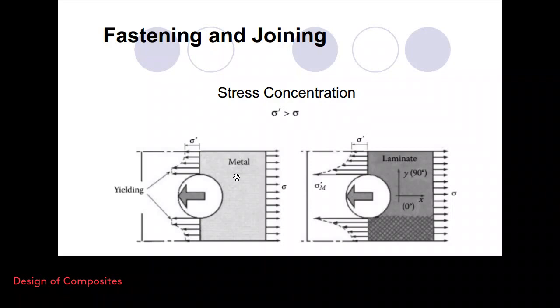Now, in case of a metallic material, if you apply a tensile stress, certainly you see that there exists a stress concentration around the hole, and in fact there is a certain region at which the stress exceeds the yield stress, and as a result you see yielding. But in the case of a composite material, you don't see it, because it doesn't possess any yield deformation, so it fails immediately. Generally, the epoxy, for example, is a brittle material. In fact, many of the fiber materials are brittle as well. So you see a sharp increase around the hole.